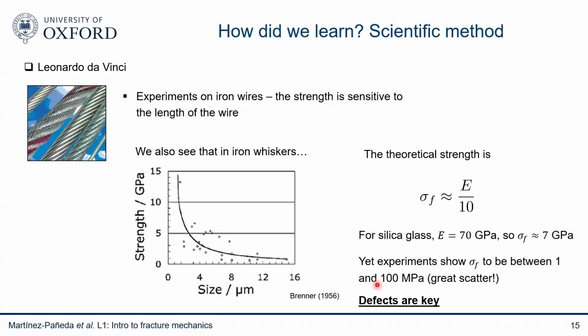And this is because of the role of defects. Different samples that look identical to our eyes actually have defects that are different, that we don't see with our eyes, but are inside, microscopic defects of different sizes, and those defects will govern the strength of my material. So I'm testing samples that I think are the same, but in reality they're very different. That brings the scatter. And I'm testing samples that, to the naked eye, look smooth and defect-free, but in reality they have microscopic defects, and that brings a change relative to the theoretical strength. So defects are important.